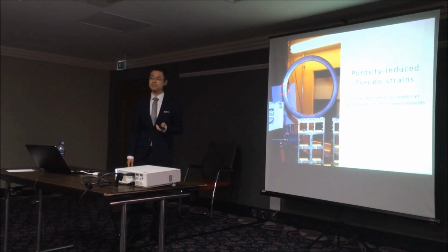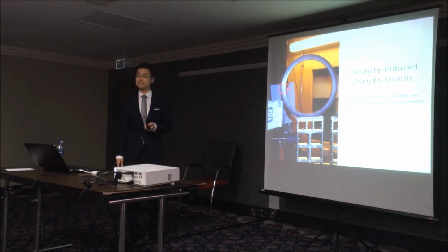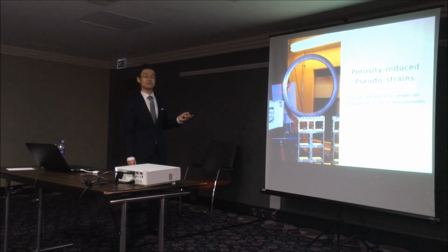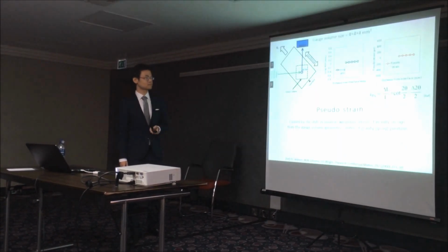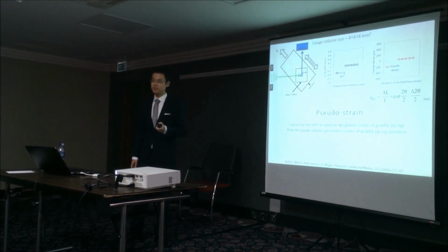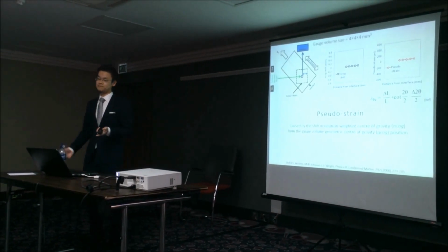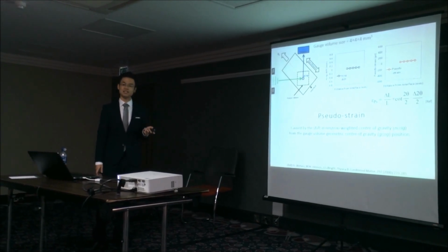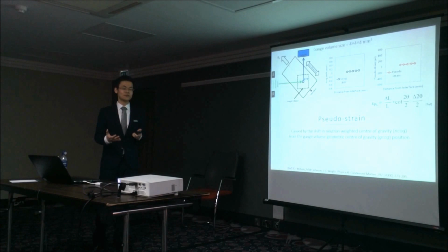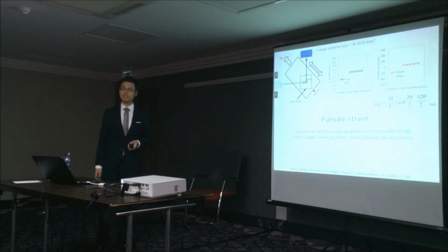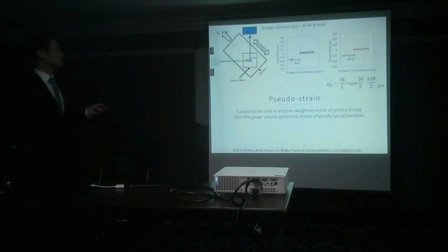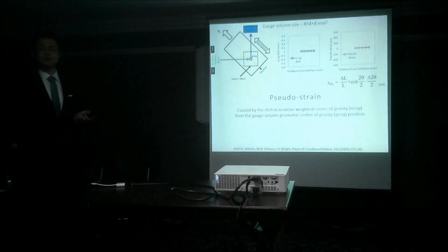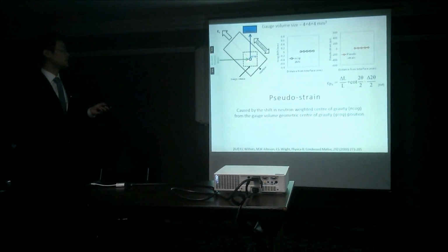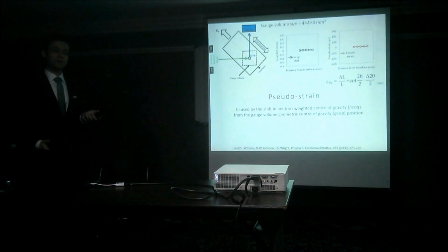And here it is suitable for me to touch on the porosity-induced pseudo-strains. Let's take a plain view from the highlighted cross-section. So the gauge volume used in this study was a symmetrical one. And pseudo-strain is caused by the shift in neutron-weighted center of gravity from the geometric center of gravity of the gauge volume. For a completely filled gauge volume inside a sample, we can expect the neutron center of gravity to be aligned with the geometric center of gravity. And therefore, we can assume there will be no pseudo-strains.